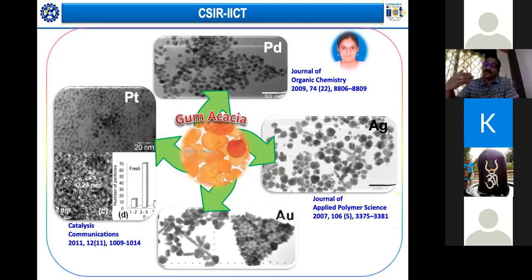So to start with, we took a UV spectrum, and by looking at the surface plasmon resonance peak, we could understand that it was silver nanoparticles. But until we saw it in a TEM, we were not very clearly sure. Then we saw that these were silver nanoparticles. And then we did gold, which was also very easy. We did it at room temperature. When the concentration of this gum was increased, we observed that it took the form of a template like this. You can see it's a pyramid with all different faces. It formed a template on which these gold nanoparticles got nicely arranged. This decoration of gold nanoparticles on such a template proves that this material can also be used as a template for the synthesis of metal nanoparticles in different shapes and forms.